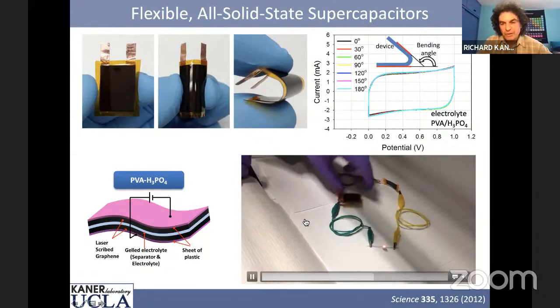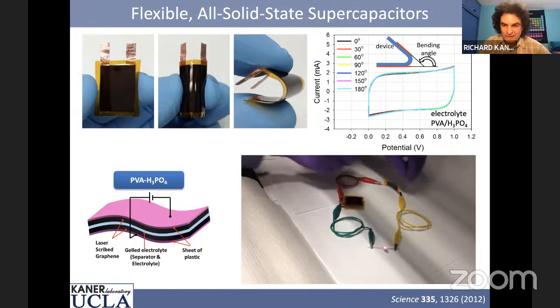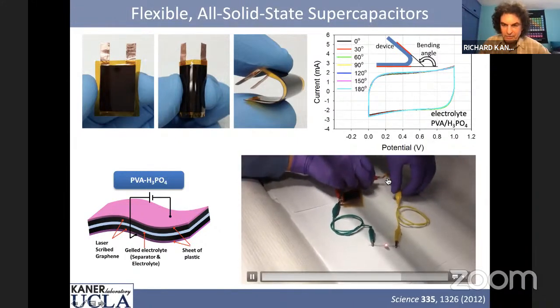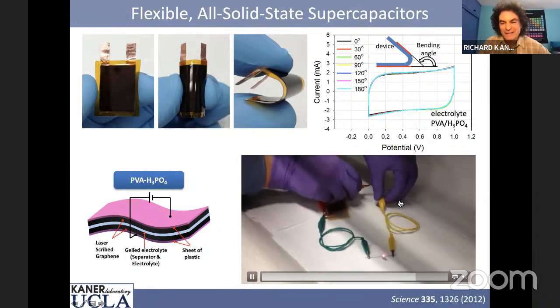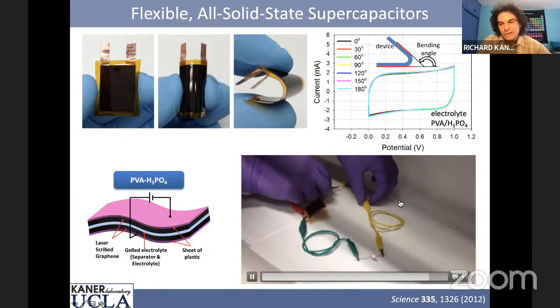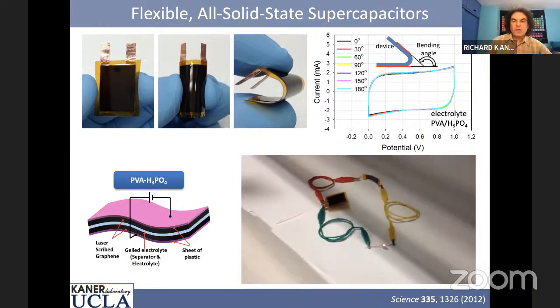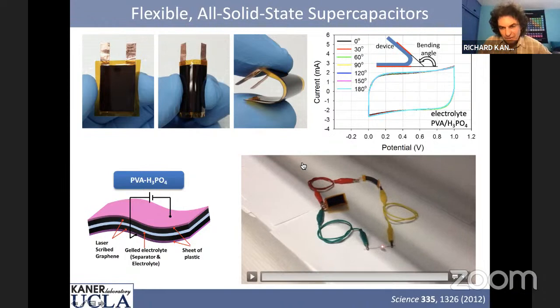And for good measure, my students took a piece of graphite oxide that was reduced. So this is chemically reduced graphite oxide, and they put it in line as a conductor. So we just wanted to demonstrate that you can use this chemically reduced form of graphene or laser reduced form of graphene as both a conductor and an energy storage device.